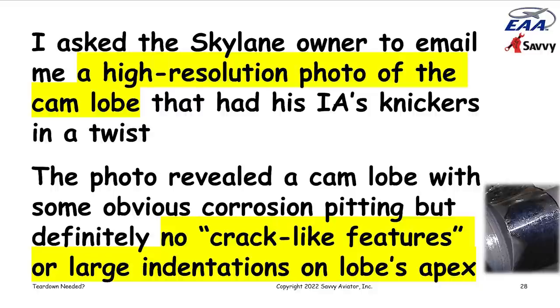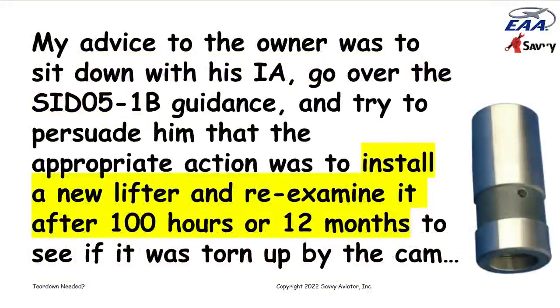So I asked the Skylane owner to email me a high resolution photo of the cam lobe that had his IA in a twist, the cam lobe that was exposed when the cylinder came off. The picture of the cam lobe that he sent back showed some corrosion pitting, but nothing like crack-like features or large indentations that would clearly have penetrated the carburized layer. So I said, that looks okay. I think what you ought to do is follow the let the cam vote guidelines in SID 05-1B and just throw some new lifters in there and check them next year and see what happens.